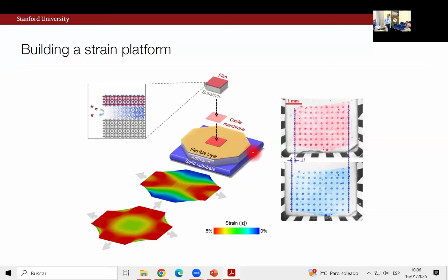So the schematic is very simple, but I think it's working pretty well, that we can laminate a membrane onto these sorts of Kapton sheets. We can stretch or apply stress in the far field. And these are finite element simulations trying to make this as homogeneously uniaxial as possible, and this little square is a sample, or biaxial strain, right? So we haven't really explored this degree of freedom, but I think, again, this is an interesting opportunity, right?